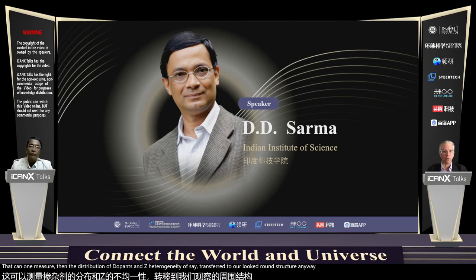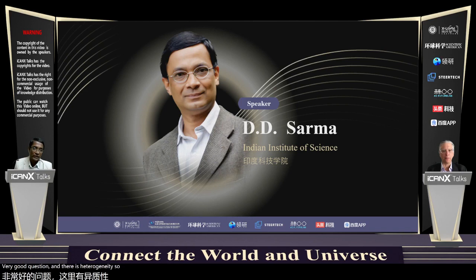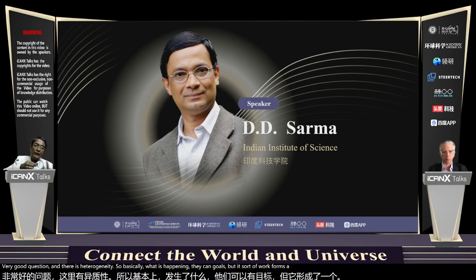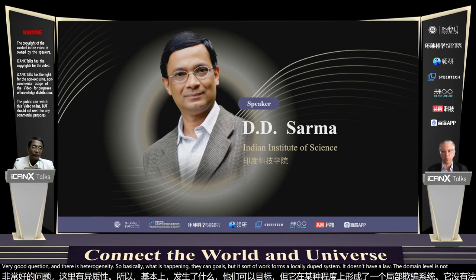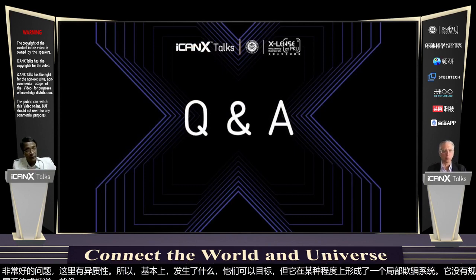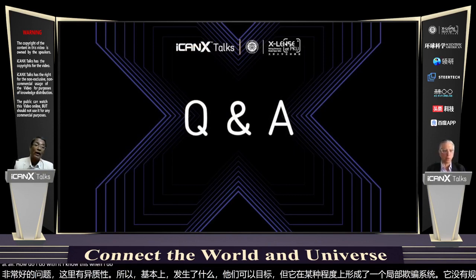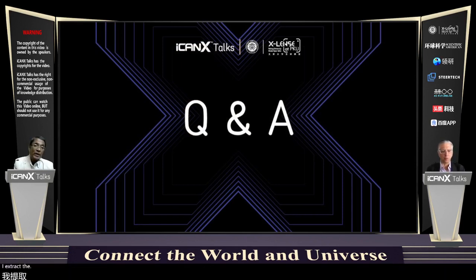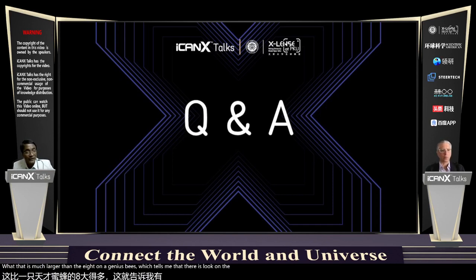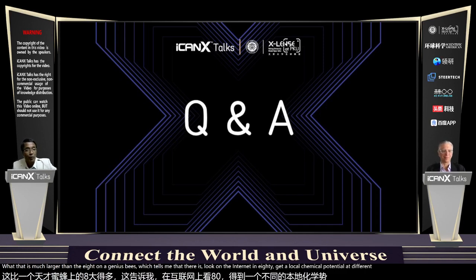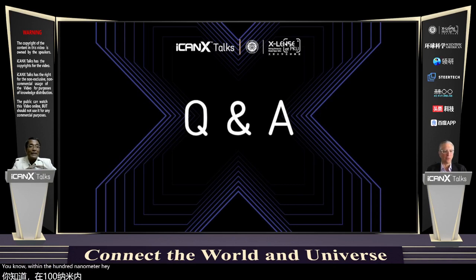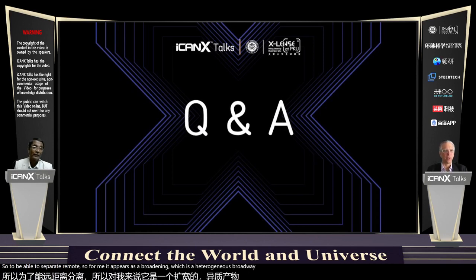Very good question. And there is heterogeneity. What is happening is that lithium dopes, but it forms a locally doped system. The doping level is not enough for it to be a totally metallic system of free electrons running around. How do I know this? I know this when I extract the spectrum corresponding to the metastable phase. It always has a width that is much larger than the homogeneous phase, which tells me that there's local heterogeneity. There are local chemical potentials at different spots, even within the 100 nanometer scale that I'm looking at. So I need a much finer probe to be able to separate them out. For me, it appears as a broadening, which is a heterogeneous broadening in homogeneous broadening.